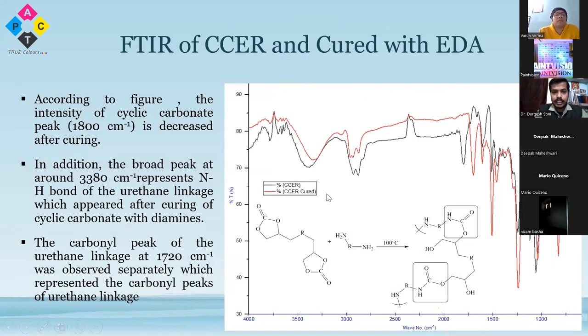So again, in this reaction, this is the cyclocarbonated epoxy resin. When it was cured with the diamine, the urethane linkage was obtained. We can see also at 1800, this peak disappeared completely. And the black one shows the original CCER cyclocarbonated, and in the red we can see at 1800 there is no peak, and a new peak at 1720 corresponding to the carbonyl group, and at 3340 corresponding to the hydroxyl group emerged, which confirmed the formation of urethane linkages.